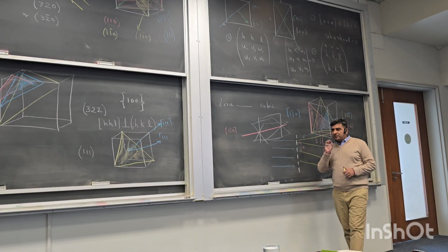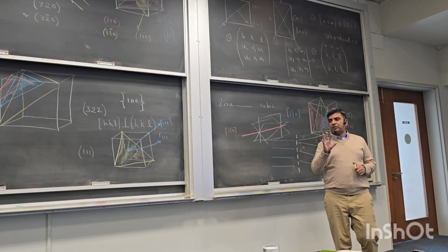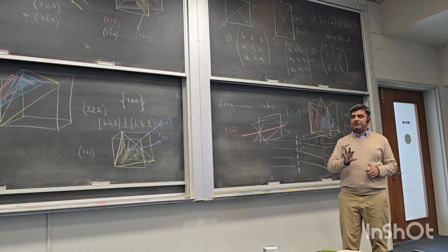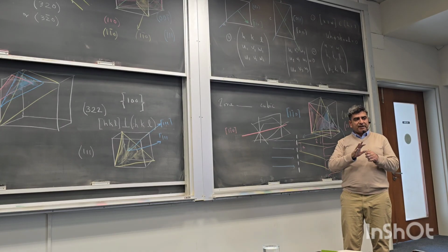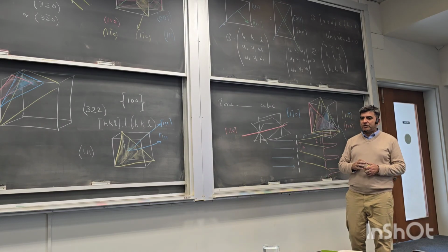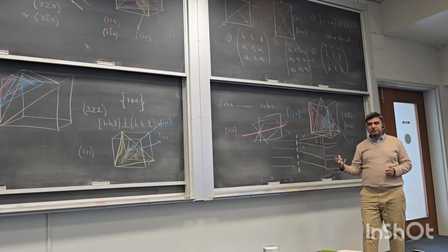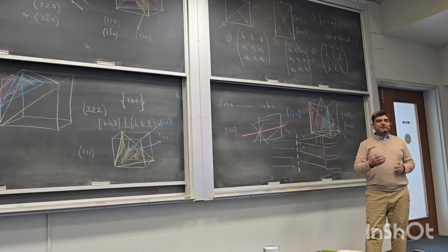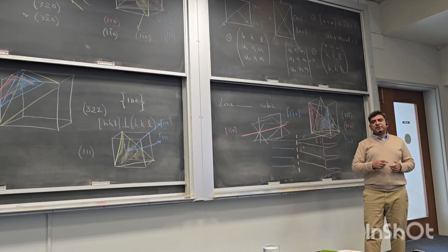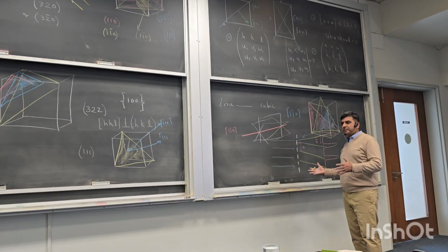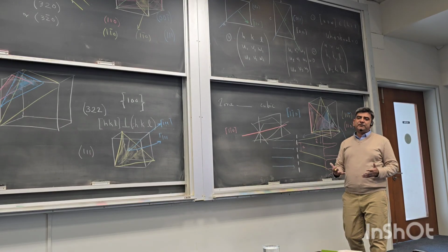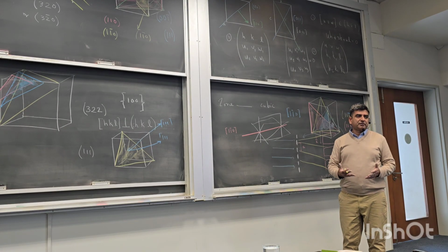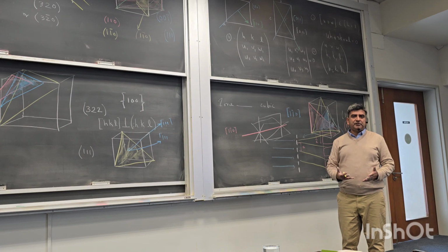So you shine some kind of radiation onto solids, and by looking at the directionality of the scattered radiation you can tell what the structure of that solid is, what space group it belongs to. And then it becomes an inverse computation problem: you get a scattered pattern, and from that you have to infer the structure, the space group.